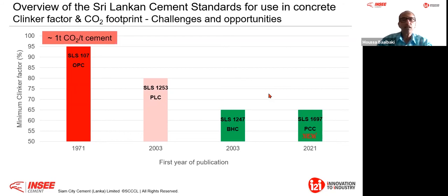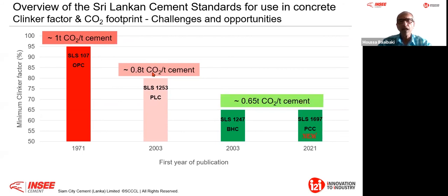But you agree with me, during that period, blended hydraulic cement, Portland limestone cement and Portland composite cement were all already developed and implemented in several countries. And that is what I will show you. Now, when it comes to the footprint, with the Portland limestone cement we can reduce the clinker by up to 20%, therefore CO2 can be reduced by 20%. After that, with the blended hydraulic cement and the new Portland composite cement, I can reduce the clinker by up to 35%, therefore I can reduce the CO2 footprint by up to 35%. And this becomes very significant.